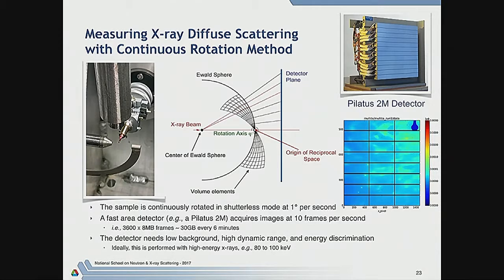There are gaps between the chips, so you have to do three different positions. But these detectors have a very low background, very high dynamic range, and we're particularly interested in doing these at very high energy with the new generation of cadmium telluride detectors.